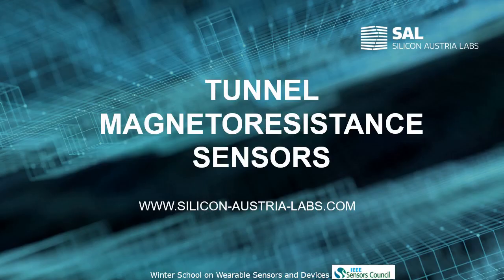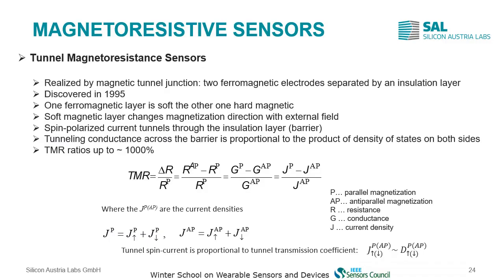Then let us move on to the tunnel magnetoresistance sensors. TMR sensors are made of a multilayer stack similar to GMR sensors, where we now have two ferromagnetic electrodes separated by an insulating layer. This is the important difference compared to the conducting layers we used in GMR sensors. The effect was discovered in 1995, and one of the two magnetic layers is hard magnetic and the other one is soft magnetic. As in the case of the GMR layers, this means an external magnetic field, which we would like to measure, will change the direction of the soft magnetic layer with respect to the direction of the hard magnetic layer.